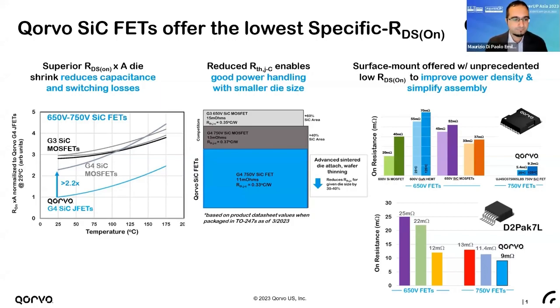Everything is good. And the main reason is that we have a somewhat differentiated technology where we use a silicon carbide JFET in a cascode configuration to make the normally off switch. And people sometimes ask, well, why cascode? Well, there are a lot of advantages and some challenges associated with a cascode, but the real reason is the superior RDSA. The lowest specific on-resistance switch of any technology is a silicon carbide vertical JFET. And so by combining that with a silicon MOSFET, you can achieve this normally off device with the least amount of die area.